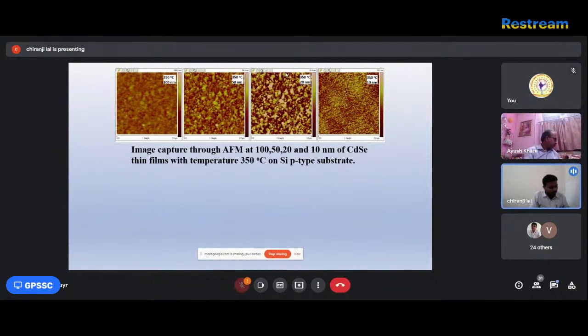AFM data show the CdSe thin film layer is homogeneous and the distribution of grains is uniform. AFM images also show that the crystalline size of CdSe thin film increases with increased annealing temperature. Crystalline size calculated from XRD data increases with the increase of annealing temperature, which also matches with AFM data.